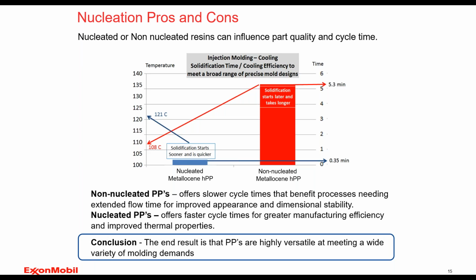Once it reaches its T sub C value, in this case with a nucleated resin, that temperature is 121 degrees C. It's going to solidify or crystallize. And once that kicks off, it's very rapid. So the isotherm representation of this nucleated grade is about 0.35 minutes. With the exact same conditions, the non-nucleated grade is 5.3 minutes. So it gives us an indicator that we are really influencing the thermal properties of this resin. And the biggest benefit is cycle time efficiency improvement with the nucleated resin.